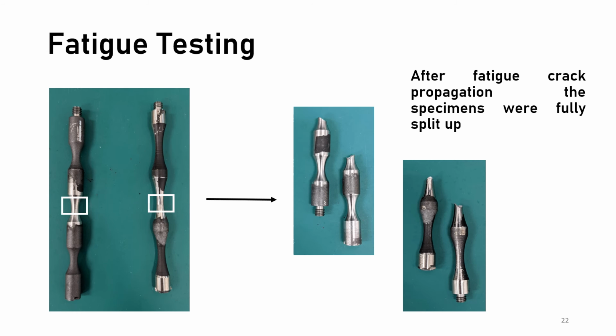Now, when conducting fatigue testing on the multi-axial specimens, the results and the way we handle the specimens is equal to the uniaxial specimens. We applied high deformation, and when the specimen creates high enough fatigue crack propagation, the specimen loses resonance, the test comes to a halt, and the specimens are fractured in another machine.